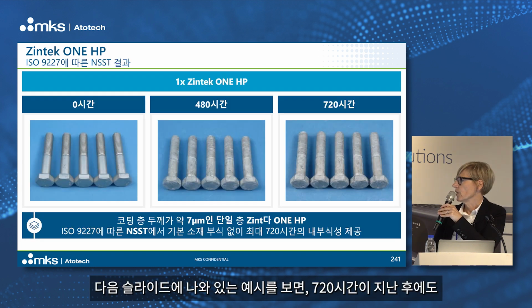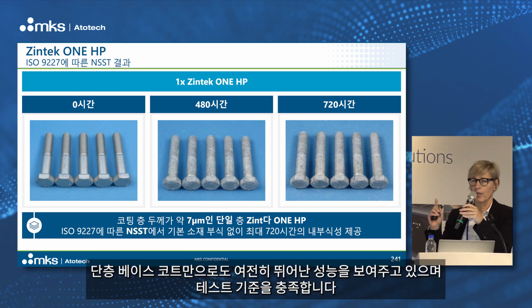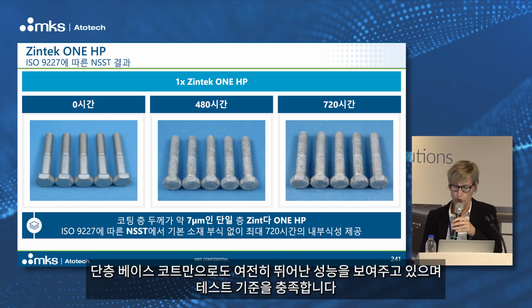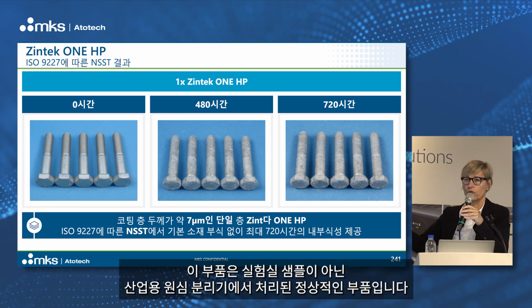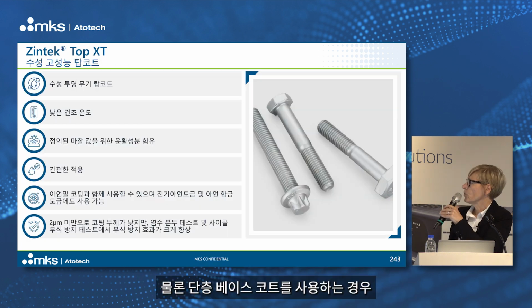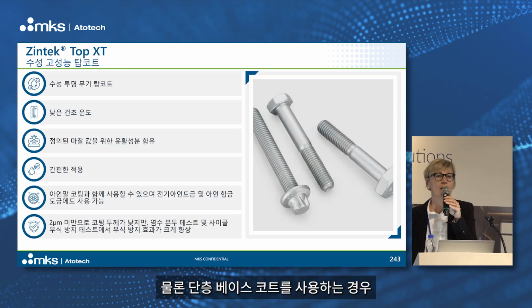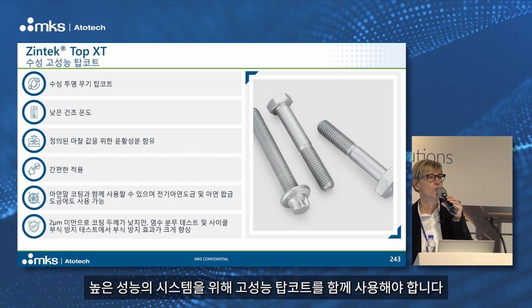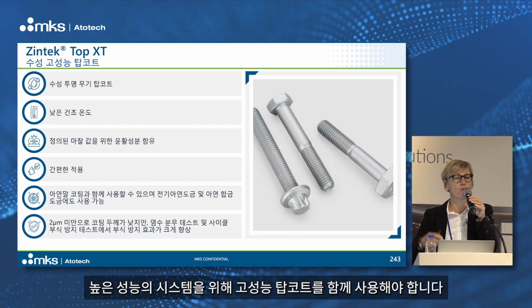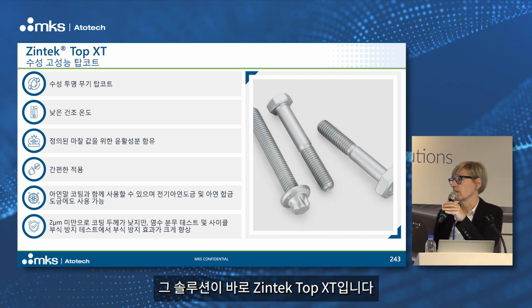If you see that on the next page, for example, after 720 hours, only one layer base coat, still performing very well and fulfilling this test. And this is coming out of a normal industrial size centrifuge, so it's not a lab part. Of course, if you have only one layer base coat and you want to have a very high performance system, you should also have a high-performing top coat, and this is our Zintek Top XT.